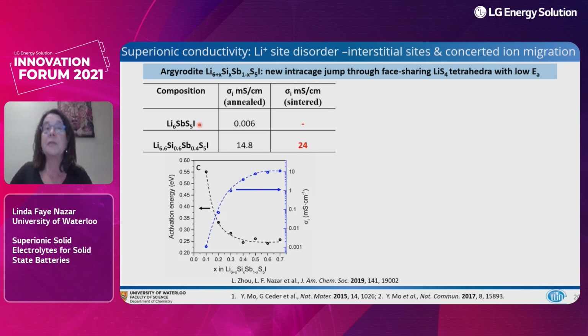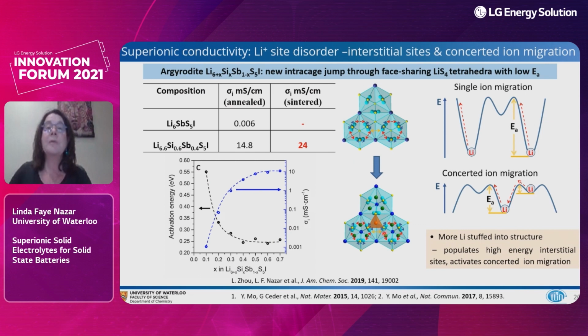The ionic conductivity of the pristine material, the antimony iodide, is negligible, whereas when you start to substitute lithium and silicon in that structure, the conductivity now rises dramatically by orders of magnitude, reaching values between sort of 15 and 20 millisiemens per centimeter. And the activation energy drops along with that from 0.5 to 0.2, quite dramatic. And so this shows the pictures of these little Frank-Kasper polyhedra, these little cages I was mentioning with their ionic transport around in the cages, and then the limiting hop between the cages.